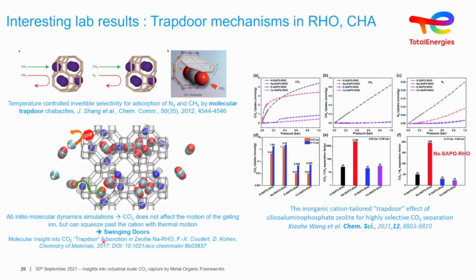But what we do think now, and again, this is coming back to the use of molecular modeling, is that these molecular insights into what we call a trapdoor mechanism may be more a swinging door mechanism, which is a result of the thermal activation of the cations inside. So the temperature of the adsorption is of importance. And this could be something of interest when we are coming back to the process. Can we play with a subtle difference in temperature to have this swinging door or trapdoor mechanism in play for different types of separations, including the CO2 separation from nitrogen or from methane, as we're seeing. So I think these trapdoor mechanisms are a way forward to start to look at zeolites. Again, it would be interesting to look at the effect of water on this, because water is in our flue gas streams often.